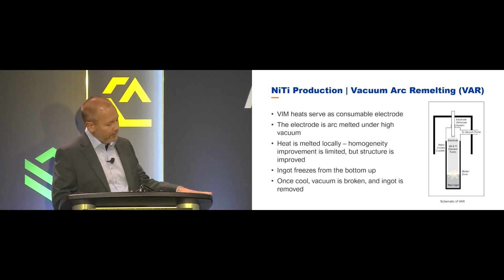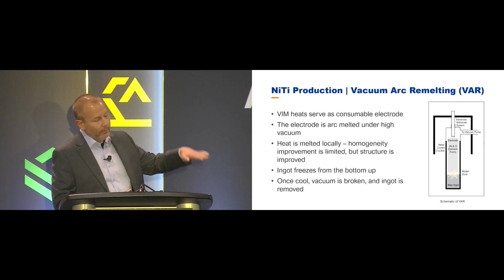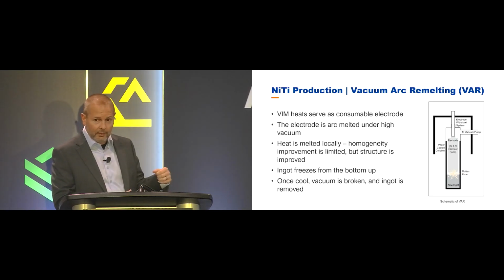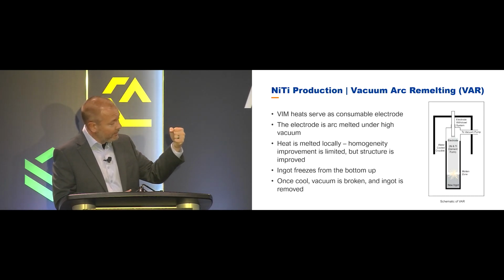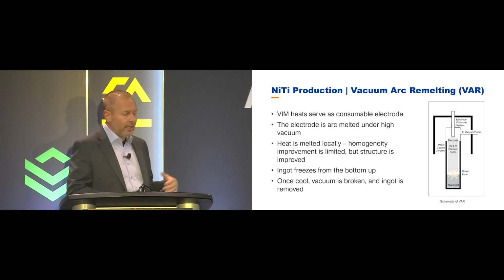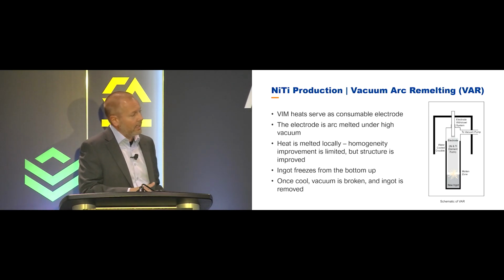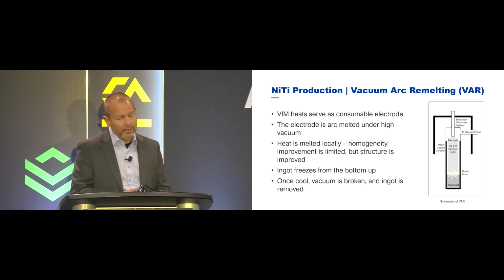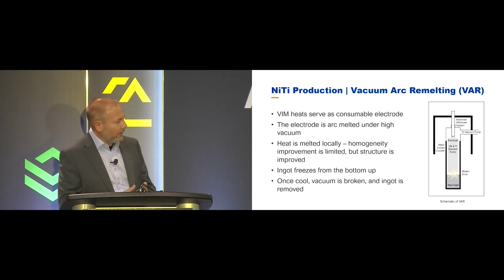And it will jump across to the copper chill plate, and it will drip off and superheat, and it will melt a new ingot from the bottom up. So we can control the solidification rate because we control how fast the ram comes down. We have load cells on the head, so we know how much weight is being lost. As we do this, we get 25 or 30 different parameters out of the furnace when we do it.